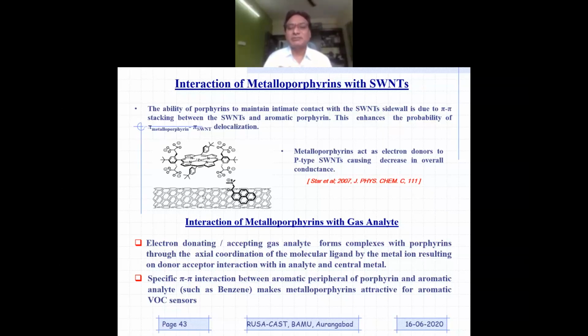As a result of that, whenever we are talking about recovery, because as far as a sensor is concerned, you need to have a good response as well as recovery time. But if you are using pristine CNT, then because of this honeycomb structure, you will have a lot of problems with the recovery of the sensor. Now, it also has poor selectivity due to limited transduction mechanism.